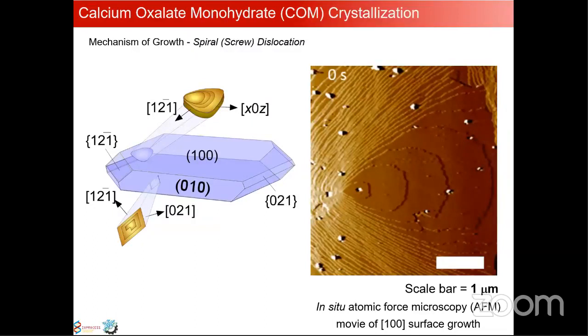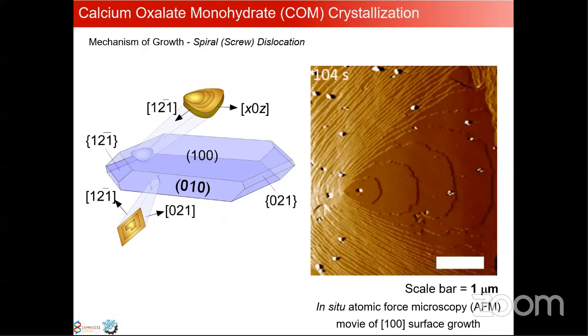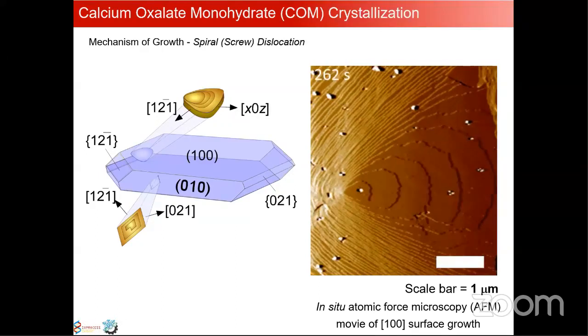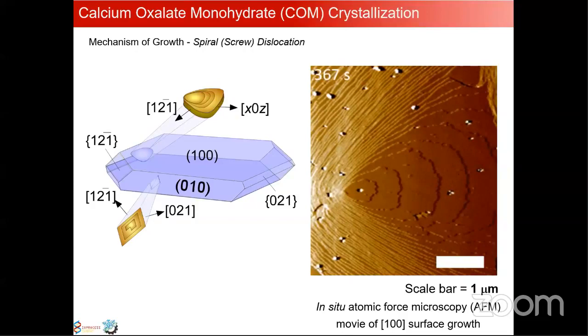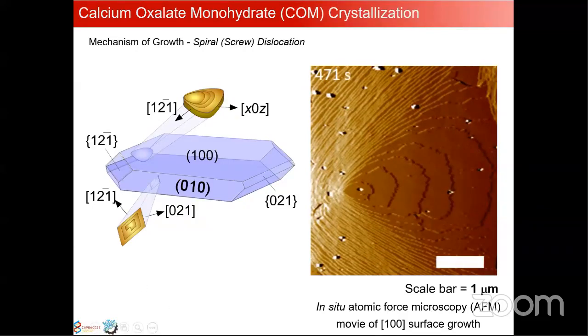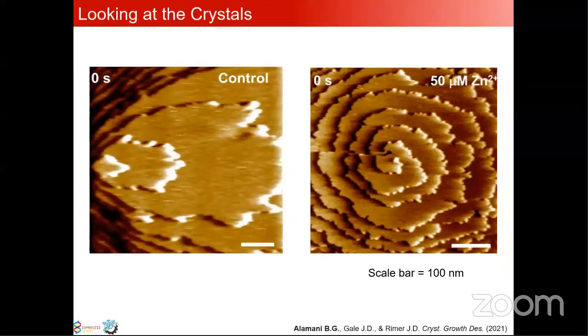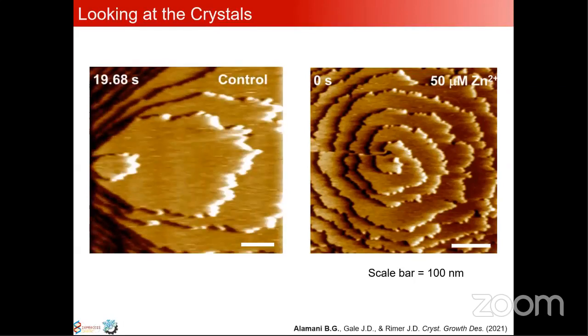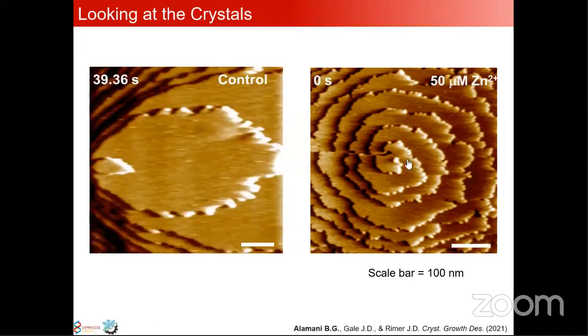Okay, so here what I will show you is the way this calcium oxalate crystal, particularly the basal surface, grows. And this movie, I hope you can see it. It shows you the way the crystal is propagating. This is in the presence of a growth solution flowing. And this was the movie I generated a couple of years ago. Now I'm going to show you the influence of zinc. Here the smaller scale bar is 100 nanometers. This is in the absence of zinc, so it grows in the usual triangular mode.